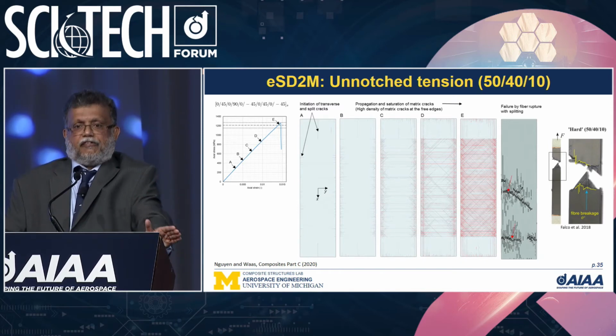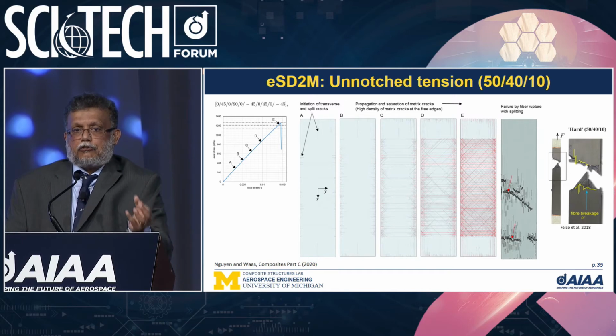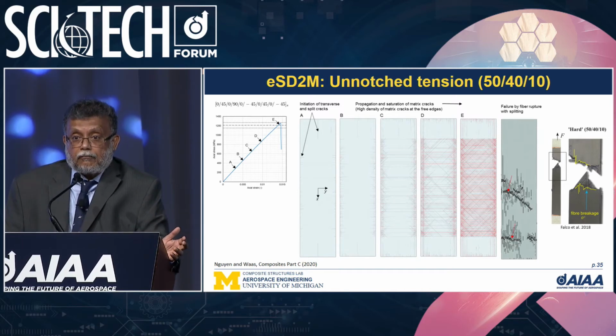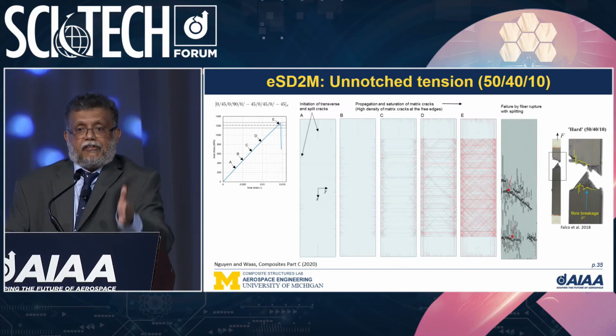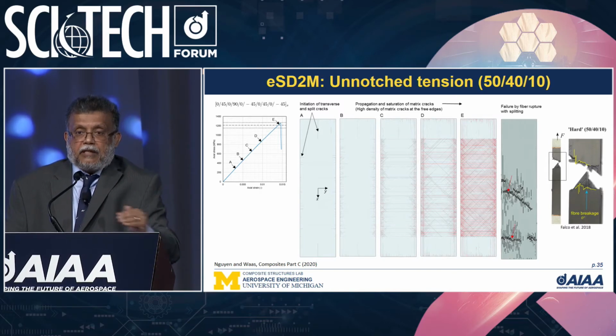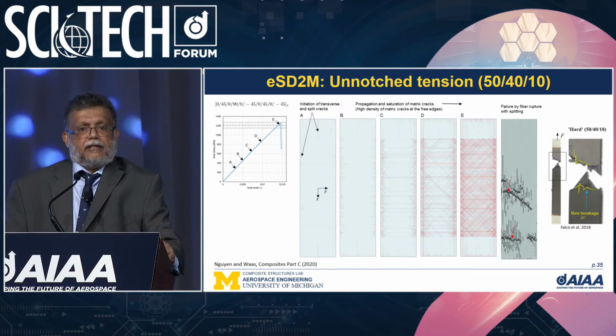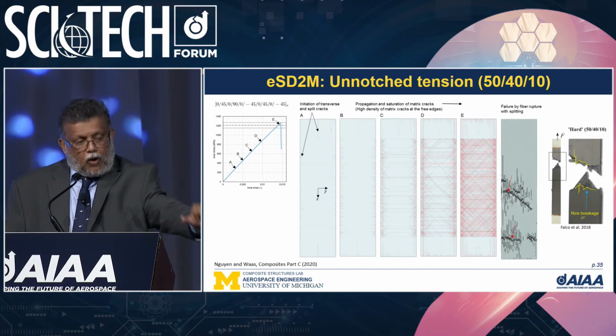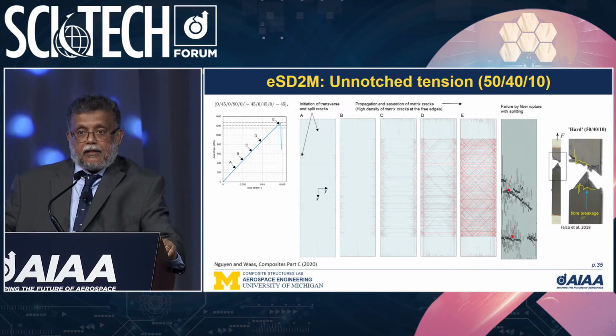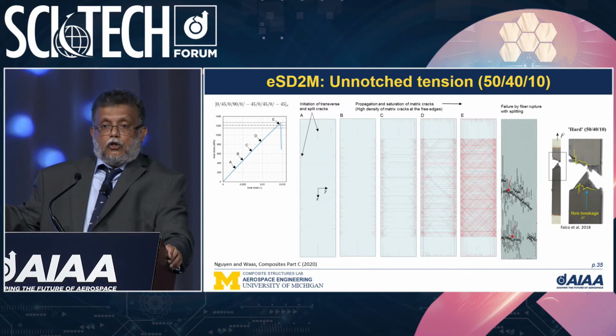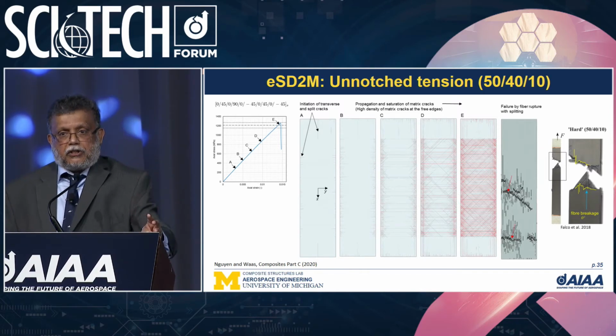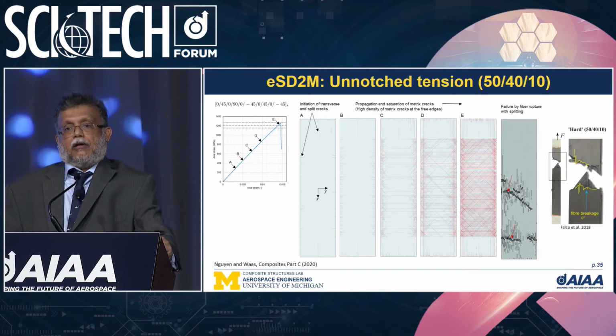That's a feature of progressive failure. When you have progressive failure in a composite, the symmetry in your initial undamaged structure is completely destroyed. So what you have at every successive load step is an unsymmetric, completely general laminate. That's the reason why your final failure in that inset looks the way it looks, with delamination, rupture, etc. Very unlike a metal specimen.